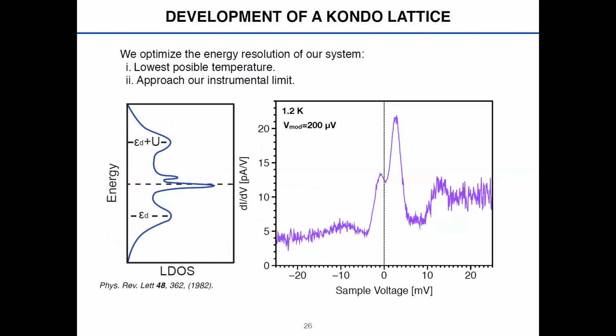First of all, measure at the lowest possible temperature, in this case 1.2 Kelvin, and then approach our instrumental limit. We do this by decreasing as much as possible the modulation of the lock-in, which in this case is 200 microvolts. And when we do spectroscopy, this is the average of maybe 100 spectra, we observe this gap that has appeared on top of the Kondo resonance, and we believe it marks that we are in this Kondo Lattice regime.